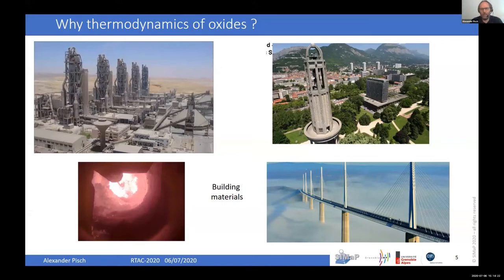On the right side is, as I said, the concrete thermodynamics. Here, it's not so much high temperature, but more aqueous thermodynamics. The cement is mixed with water and it reacts. And here, again, high quality data is needed because at room temperature or close to room temperature, thermodynamics alone is not governing the system. It's clear that a lot of phenomena in this temperature range are kinetic, and it's good always to determine whether what you observe has a thermodynamic origin or a kinetic origin. So really good data can help us